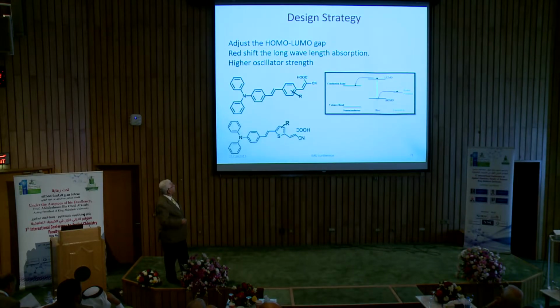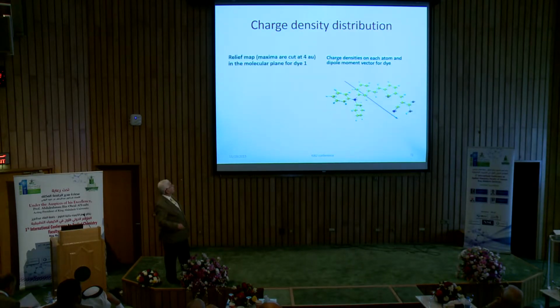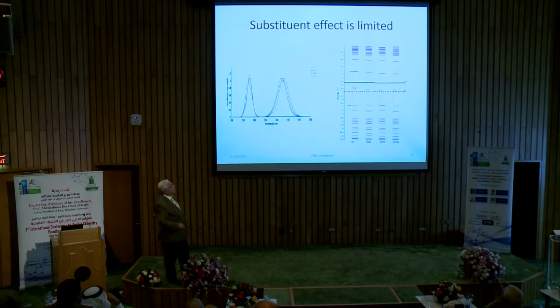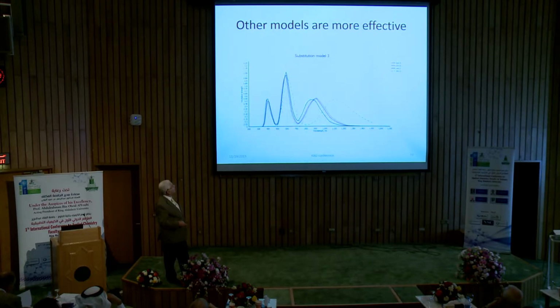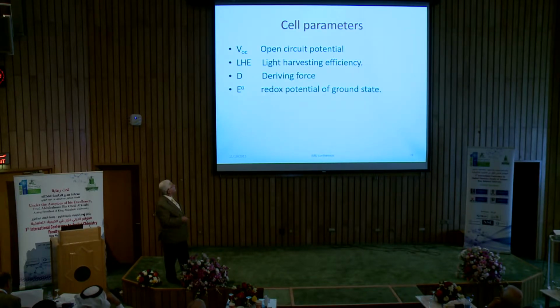A lot of calculation, sometimes positive, sometimes it's not very efficient, but anyway, we try some very typical dyes, and this dye, for example, is typical with a 12% efficiency, but substitution didn't increase the harvesting efficiency of this dye much. But this is not always the case. We have other dyes here where we could shift the absorption toward red and have more harvesting of the light. And of course, all cell parameters can be computed.